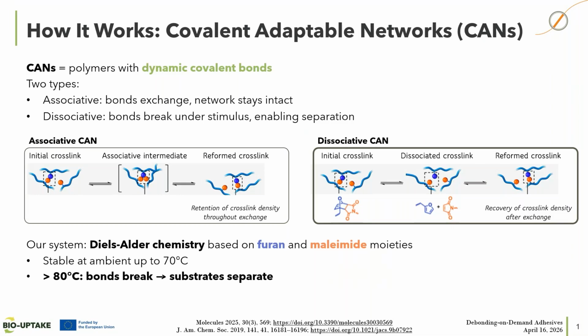And specifically, it relies on a Diels-Alder chemistry using furan and maleimide groups. So in that case, under normal conditions, typically from ambient temperature up to 70 degrees, the components remain stable and strongly bonded. But when we hit above 80 degrees, the bonds start to break in a reversible way, and this allows the separation of the substrates.